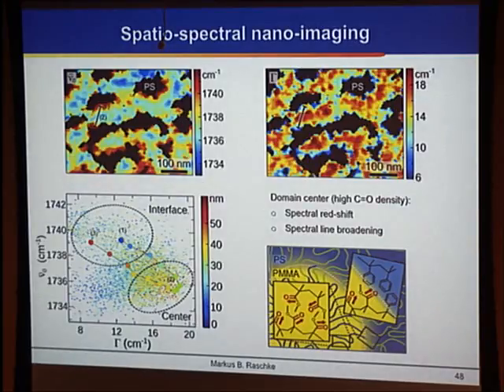And then if you do this, you see here the black regions are where the polystyrene is, where there's too low a carbonyl density. But then we can go across the PMMA region, and you see that there is a predominant blue shift at the domain interfaces, a clear red shift as you go into the center, and then we're going back out. Here, over 60 nanometer distance, is that correlation of peak frequency and the corresponding shift, and associated with it we see almost a factor of 2 doubling of the line widths. This means that the vibrational lifetime is greatly reduced as we increase the coupling between the carbonyl oscillators in the center of the domains, and then we can go back.